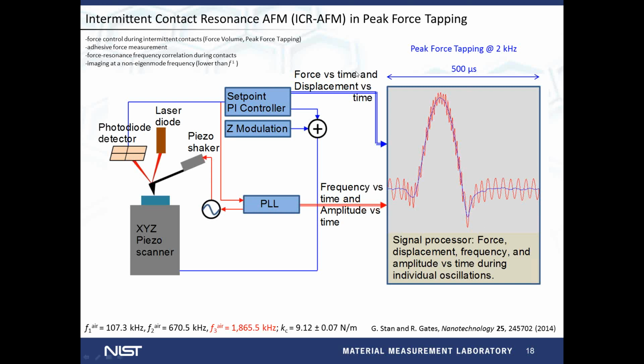The example here shows this implementation with PeakForce Tapping operated at 2 kilohertz. There are also slower frequencies that you can modulate here. The slowest, I think, is 0.25 kilohertz. So anyway, for 2 kilohertz we have an approach-retract cycle happening in 500 microseconds, and on top of that we put a fast modulation frequency from a phase-locked loop instrument, and here we see what happens.